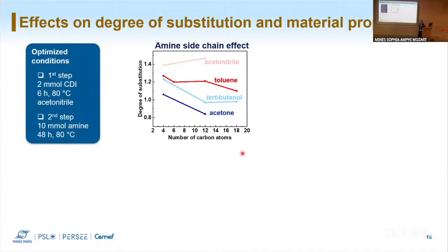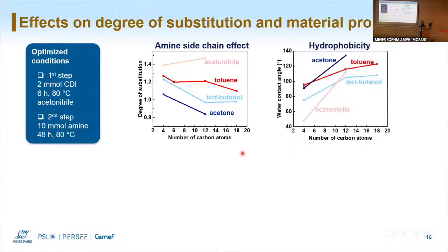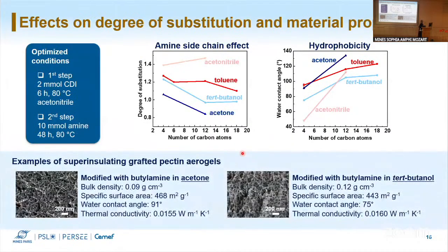So in general, we had lower degree of substitution when we were using bigger amines, and we have the highest substitution for acetonitrile. Looking at the hydrophobicity of our final aerogels, we see that even though we had lower substitution with big amines, we had higher hydrophobicity, which makes sense because we have more lipophilic chains in our material. Some examples of materials that were super insulating and with increased contact angle: modification of the aerogels in acetone and tert-butanol. So with butylamine in both cases, here in acetone, here in tert-butanol. In both cases, we have low density, we have high specific surface area, very close to our neat materials. Contact angles are increased a lot. Here we're almost hydrophobic. And the thermal conductivity remained very low, as low as we have for neat pectin aerogels.